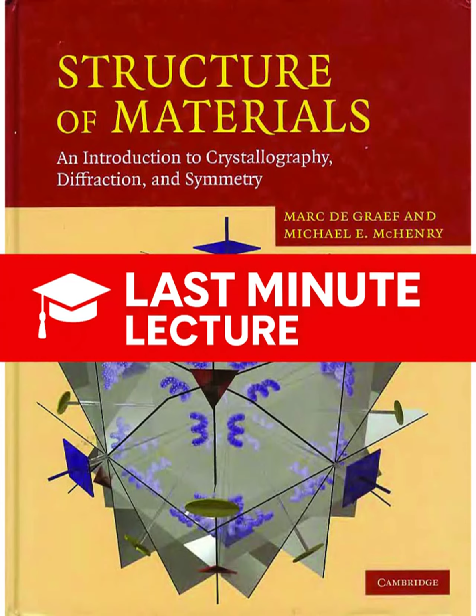Now let's look at a C-centered lattice. C adds an identical atom at the coordinates 1/2, 1/2, 0, the center of the C face. Right. When you plug the origin atom and that centering atom into the structure factor equation, and you simplify the math, the terms cancel out to 0 whenever the sum of the first two indices, h plus k, is an odd number. So h plus k must be even for a reflection to be seen. h plus k equals 2n. Therefore, reflections like 100 or 120 are systematically absent.